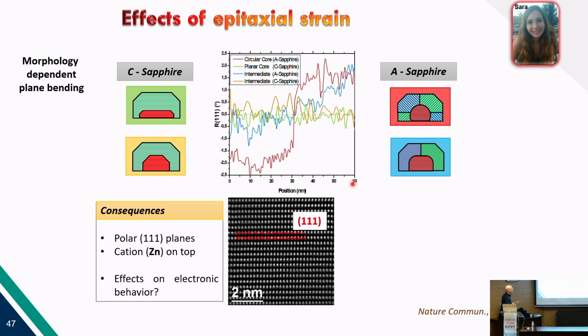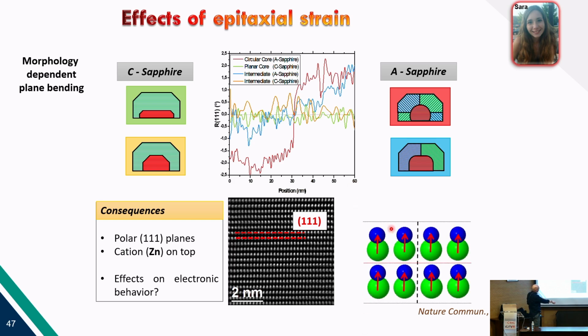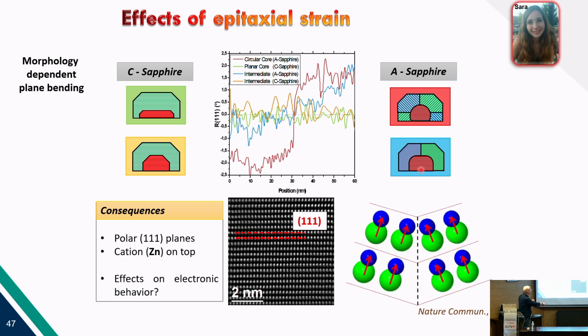But if we take into account the polarity of this material, you see that your material is composed of these dumbbells. Dumbbells because you have the cation and the anion. So what is going on when these dumbbells are flexing? It's that you are creating a potential in between them. You are creating an electric field, which is maybe not good for your material. But this is something that you don't know if you cannot see.